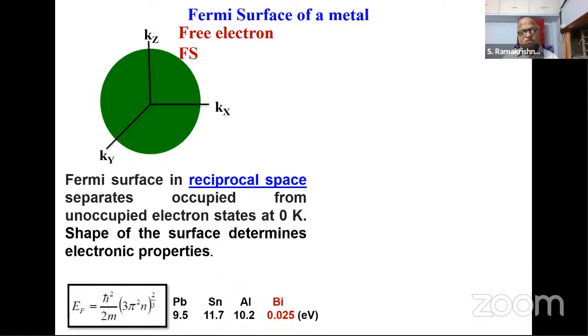You will see that for lead it is 9.5 electron volts. For tin, it is 11.7 electron volts. Aluminium, it is 10.2. You see bismuth, bismuth is only 25 milli electron volts, almost room temperature, right? Room temperature is something like 26 milli electron volts. So it's extremely small compared to all the other metals.